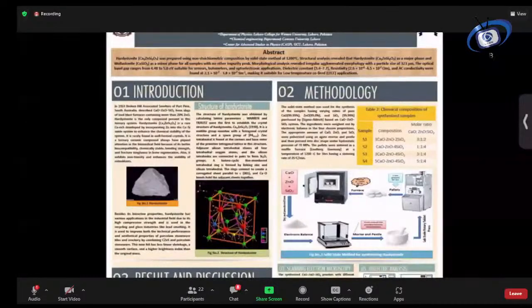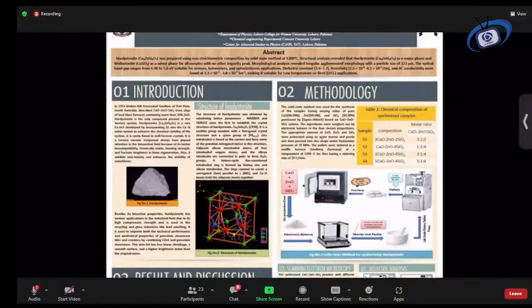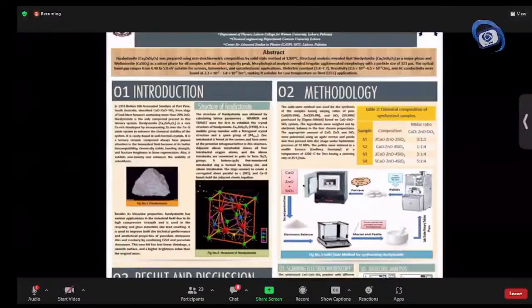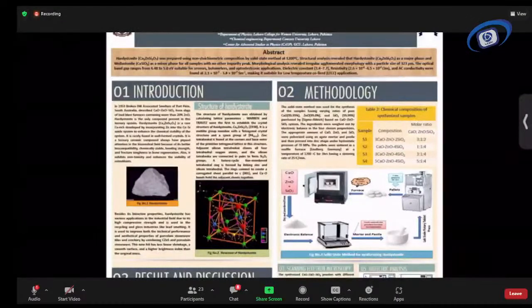where I have taken four samples with different ratios of calcium, zinc, and silicon oxide, and then pulverized them in a mortar and pestle, and then made pellets under a hydraulic pressure of 7 tons. And then I sintered the pellets at 1200 degrees centigrade for 3 hours at the rate of 25 degrees per minute. So these are the molar ratios of chemical composition inside the samples, and this diagram shows the process of the methodology.